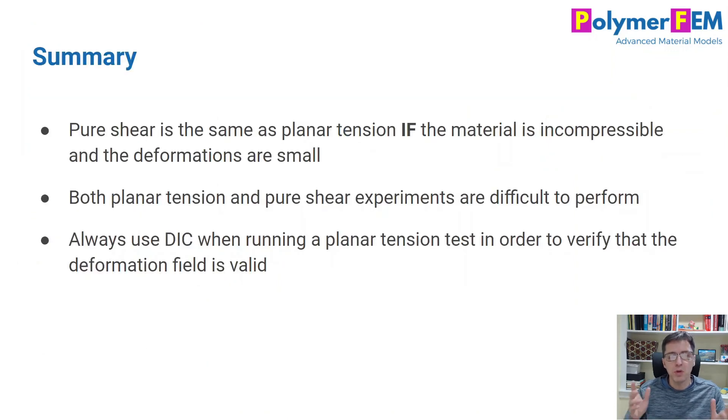So to summarize, pure shear is the same as planar tension if the material is incompressible and the deformations are small, and then you can kind of work with this. But remember, it is difficult to perform planar tension and pure shear experiments in real life. These are difficult experiments to do. Boundary conditions are hard, etc. So what I do recommend is that if you do a planar tension experiment, always use DIC, digital image correlation, to verify that the strain state is what you expected it to be. So if you have any questions, you can ask them below. We'll see you next time.